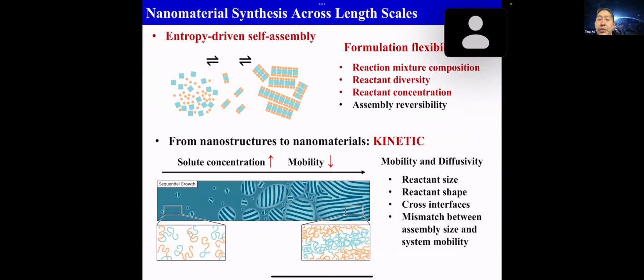As the solvent evaporates, you have a driving force to form the assembly, whether it's an enthalpic or entropic driving force. But yet when the nanostructure forms, the system mobility will be lower. But when you're trying to organize the structures through the hierarchical tiers, you need more mobility to move larger structures instead of smaller structures. So this led us to redesign the system, and think perhaps we can flip it.